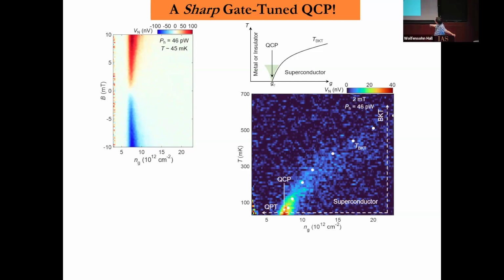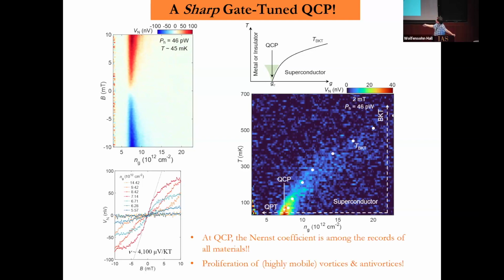So this is a KT transition. This is a superconductor—if you warm up the temperature, you see the KT transition. So everything we detect here is quantum, because it's at the end of the KT transition as we go to the limit of zero temperature. There you see the strongest fluctuation. So everything we see here is quantum fluctuation, and that's the quantum critical point. At this point, this fluctuation really rapidly develops and gives you a very large signal.